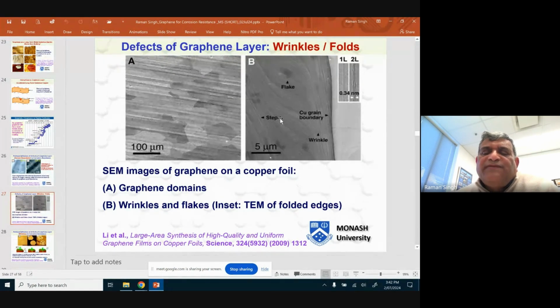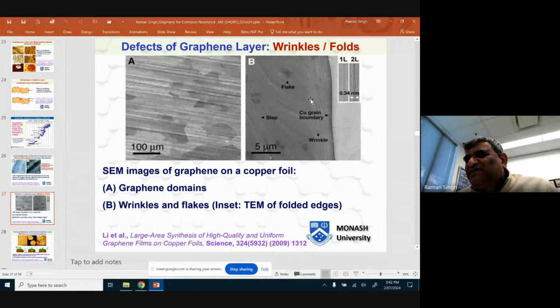When you develop graphene on any metallic material by the process of chemical vapor deposition, it invariably develops wrinkles for a very interesting reason. Graphene is one of the very few materials which has negative coefficient of thermal expansion. What does that mean? That when you cool it, graphene expands. So after CVD at the temperature of 900 or 1000 degrees Celsius, when you cool down, graphene expands and metal underneath contracts, and it adds to formation of more and more wrinkles.